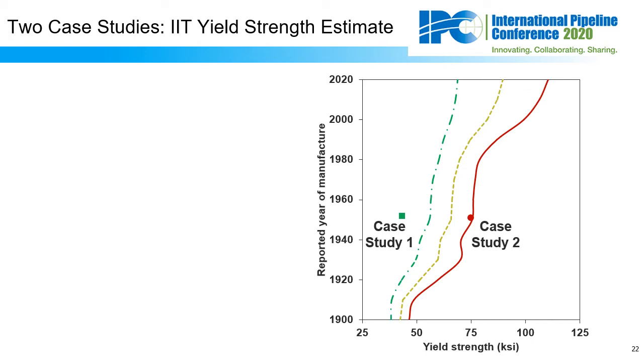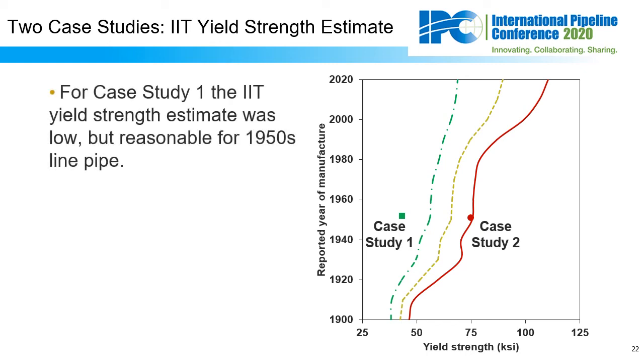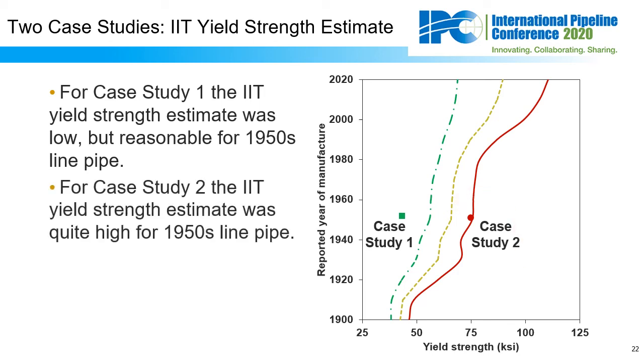Let's take a look at how our NDE data for yield strength mapped to the historical trends that we built. For case study 1, we see that the yield strength is slightly below the mean line. And for case study 2, we got a yield strength that is 2 standard deviations above the mean line. So that tells us that case study 1 is low but reasonable for the 1950s, but case study 2 is a yield strength that is quite high for 1950s line pipe.